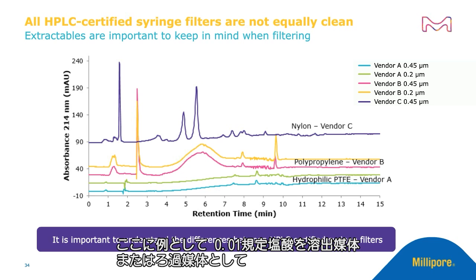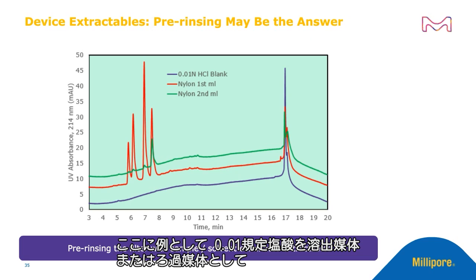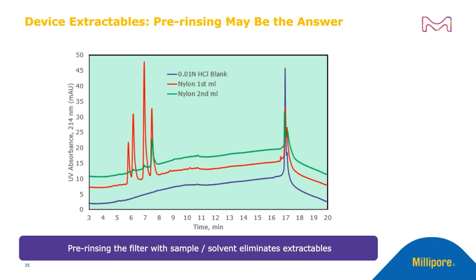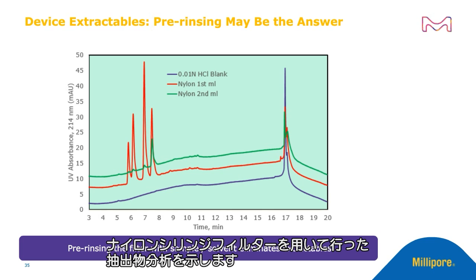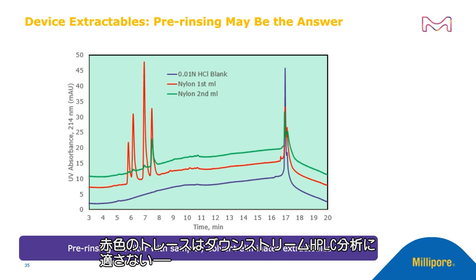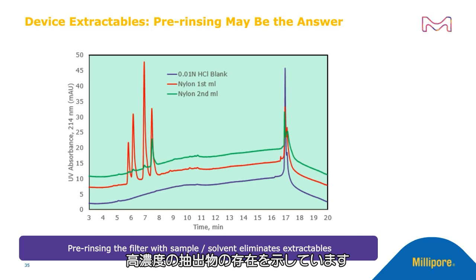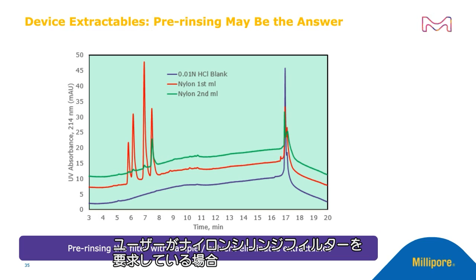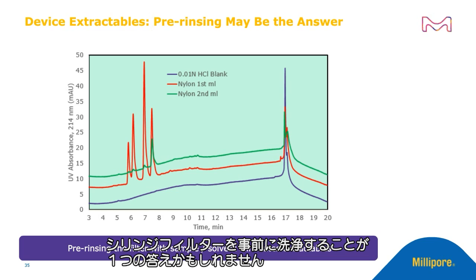Here is an example of extractable analysis that was done using a nylon syringe filter using 0.01 normal HCl as the dissolution medium or as the filtration medium. The red trace indicates that there is a high level of extractables, which will not be suitable for downstream HPLC analysis. But if your method calls for using a nylon syringe filter, pre-rinsing this syringe filter may be an answer.